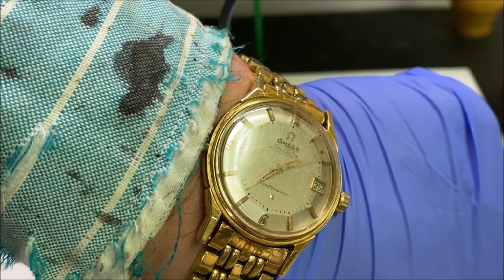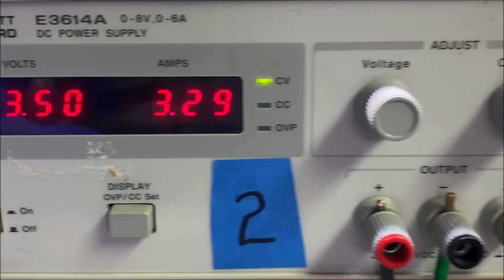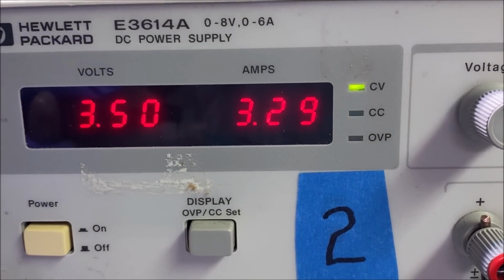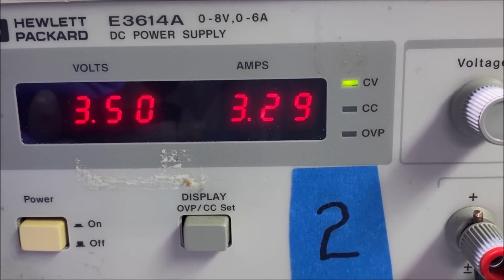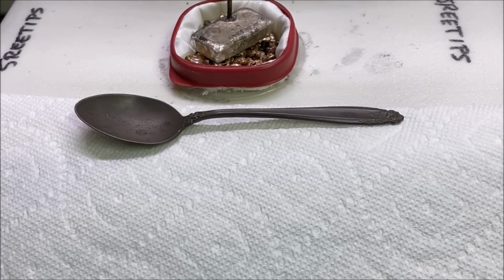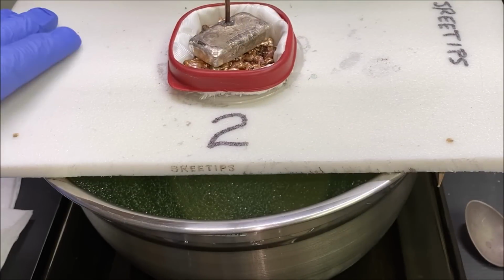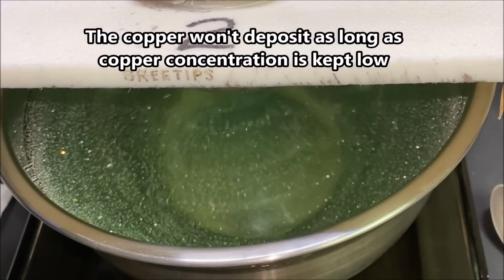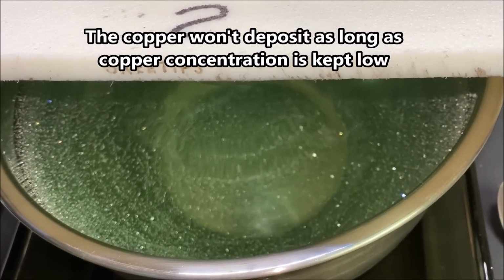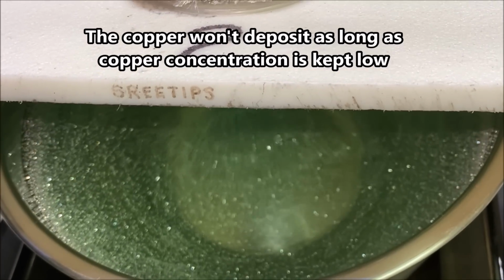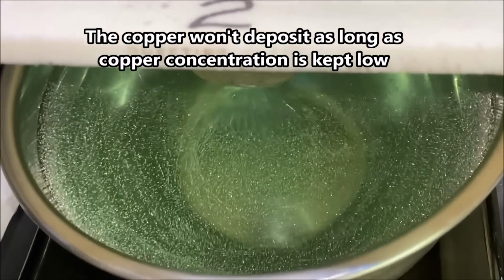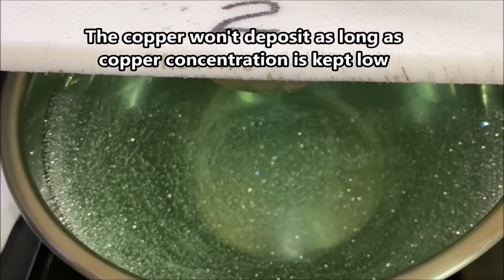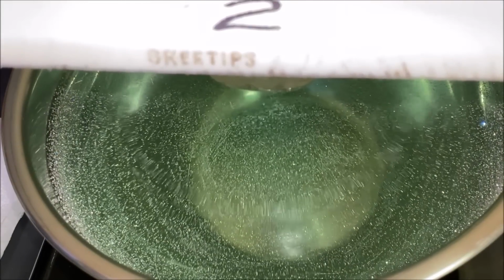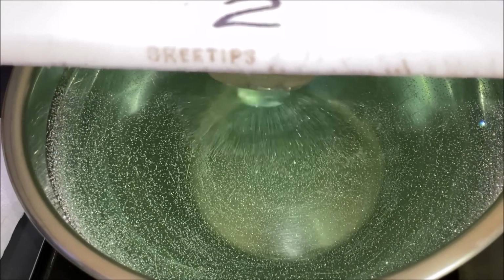I started the cell at about 12:30, so it's been running for about 1 hour. We got almost 3.3 amps going through it. If you look down in here, this is what we got going on already. You can see it's already starting to take on a blue tint, and that's from the copper that's in the impure silver that we're adding into the anode basket.